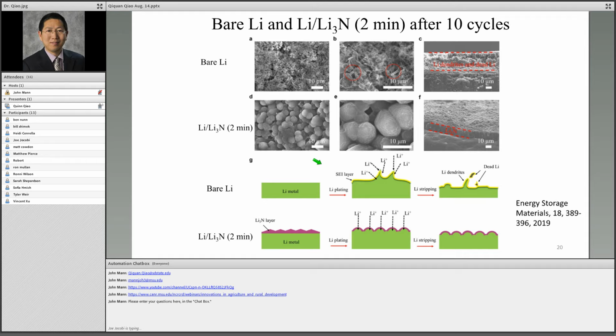And then here I show the morphology. With this lithium nitride, you grow a very compact layer. If you don't have this lithium nitride, you see lithium dendrite growth here. Sometimes this dendrite growth can be very long, penetrate the electrolyte, and then short your batteries. Even if they don't short the batteries, some of these will break off from the dendrite and be isolated in the electrolyte, causing a loss of lithium. Because lithium is the active material, you have to keep a certain amount there so your battery can run.